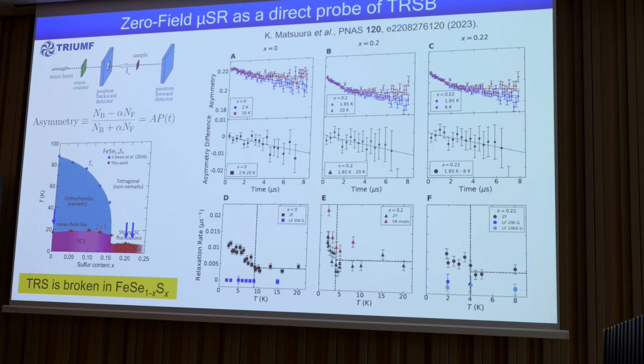We used three different samples: iron selenium, and two samples in the FeSe1-xSx series. In all of these samples, we actually see the enhancement of the zero field μSR relaxation rate below TC. This is an indication that we have static internal magnetic field appearing below TC, which indicates that time reversal symmetry is broken in this series. So this fulfills the requirement of the Bogoliubov-Fermi surface.